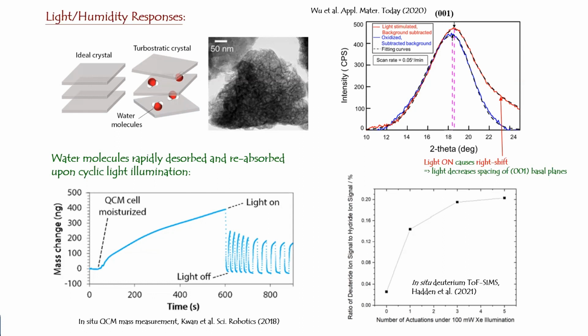all the experiments that we have carried out show that this is due to this very special structure of the material that we call turbostratic crystal structure. So a normal ideal crystal would have this ordered arrangement. So you have atomic planes and they are very regularly arranged. But in this type of material, there is a lot of water intercalated inside. So these water molecules actually perturb these crystal planes. So that's why if you look at the material in a TEM, you would never see the usual ordered image or contrast that you would see. You will see all these fuzzy type of contrast, which is indicative of this so-called turbostratic crystal structure.